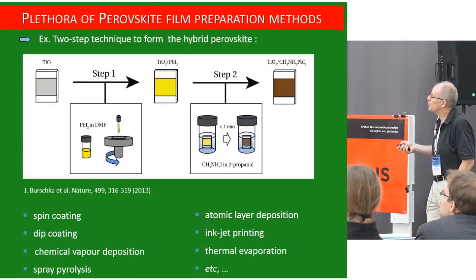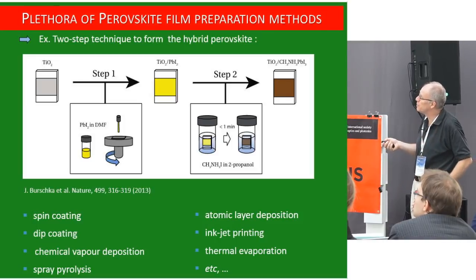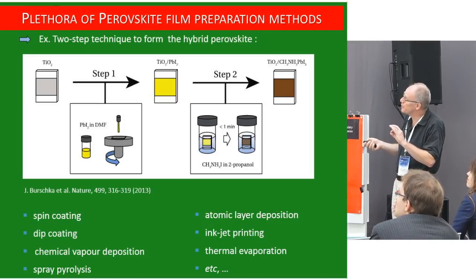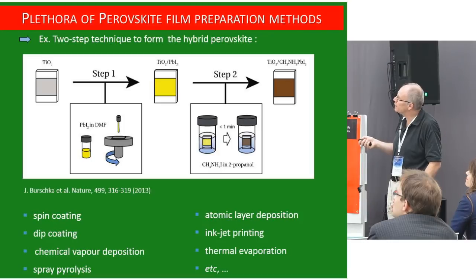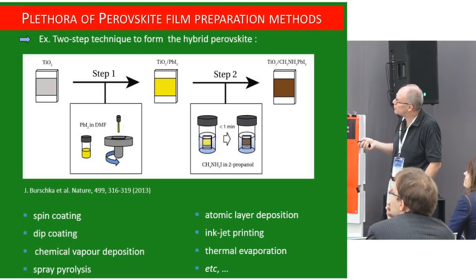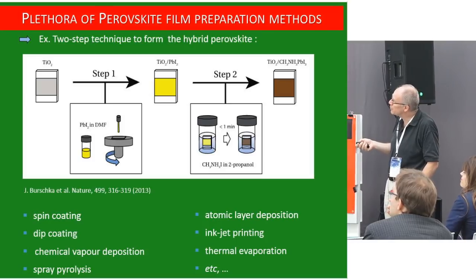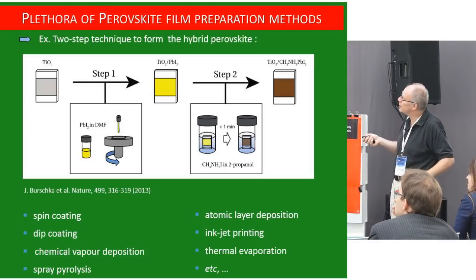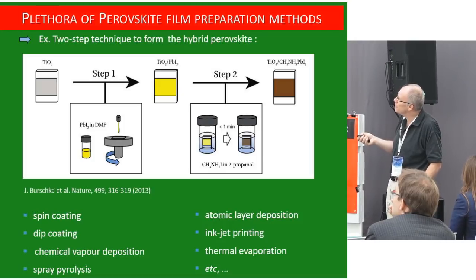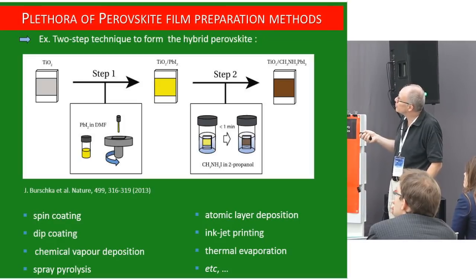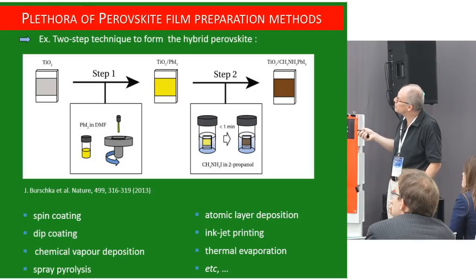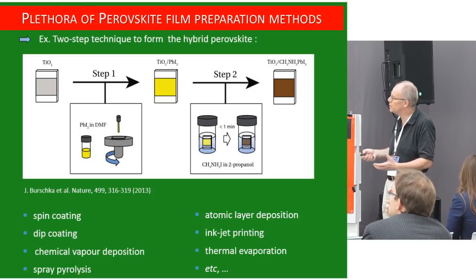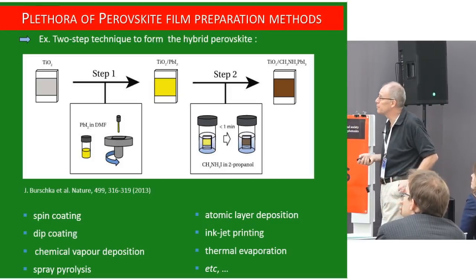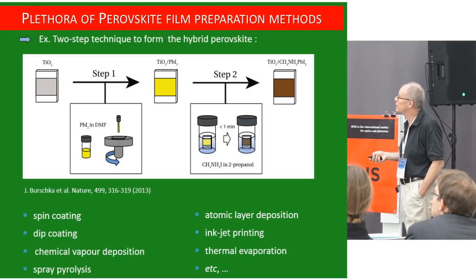This is one way of doing it. You start with the TiO2, perhaps. There are also a lot of different substrates. Now the TiO2 nanoporous layer is much, much thinner, just a few hundred nanometers, compared to the dye-sensitized cell. You start from there, then you have maybe a solution of lead iodide in a solvent, DMF. You spin coat the solution, and then you form a lead iodide layer in the porous TiO2. Then you take a methylammonium iodide salt in another solvent, and then you convert to methylammonium lead iodide on TiO2. So that's the simplest way of doing it. But you can do it with evaporation and other methods as well, of course. But this is how we typically do it at EPFL.